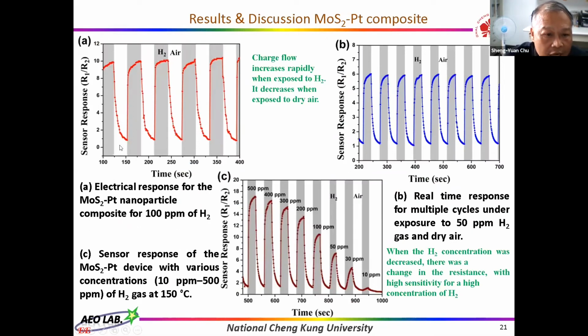Figure A shows the electrical response of the MoS2-Pt nanoparticle composite to 100 ppm of H2, and the sensor response can be up to 10. And Figure B shows the real-time response for multiple cycles under exposure to 50 ppm hydrogen gas and dry air, and the sensor response can be up to 6. From these two figures, we can see the current flow increases rapidly when exposed to hydrogen, and it decreases when exposed to dry air.